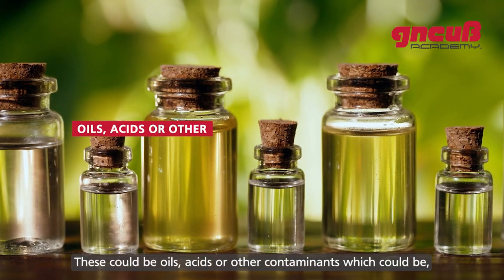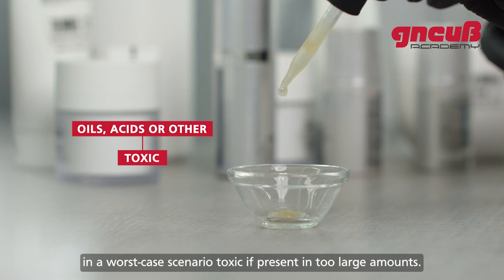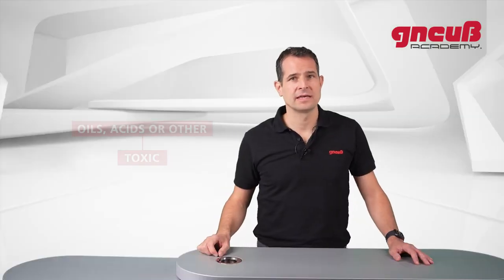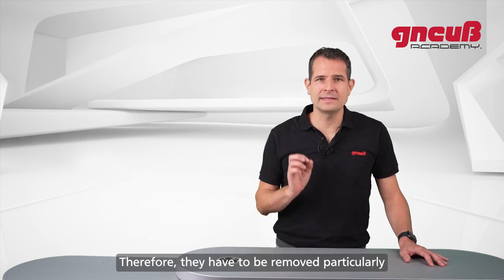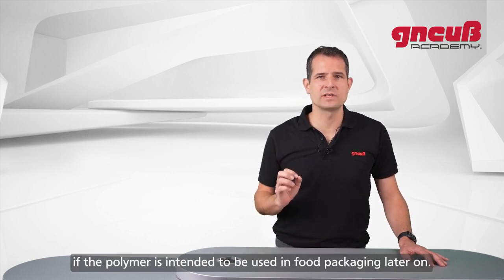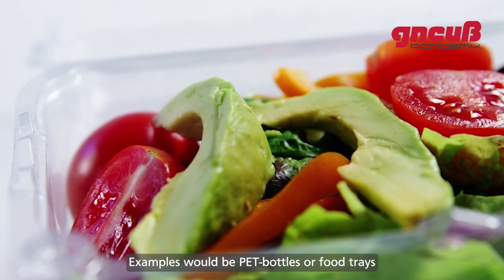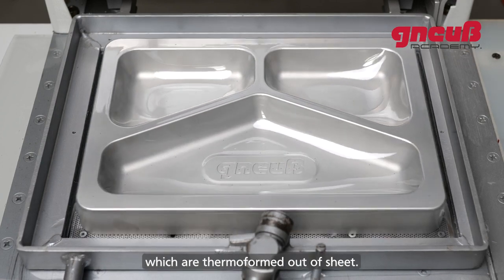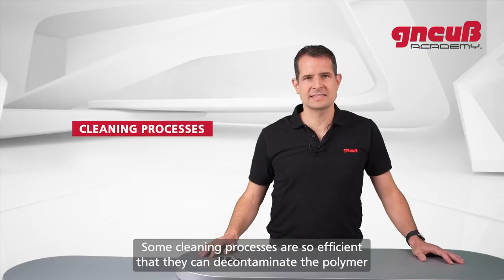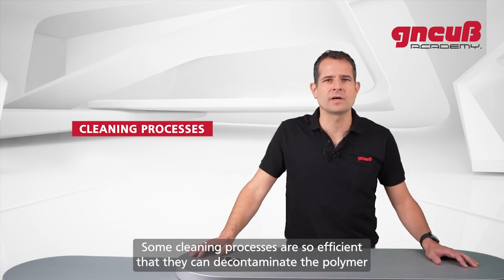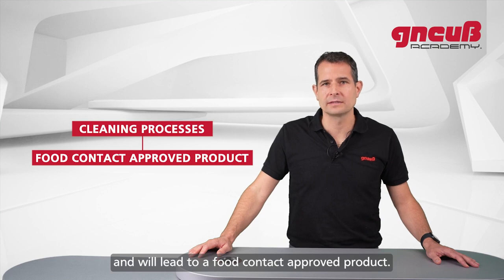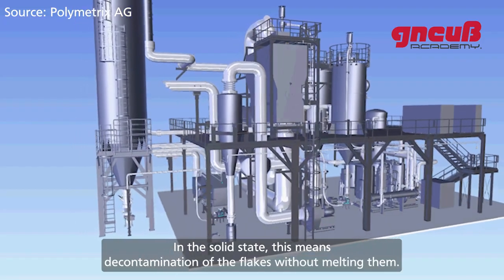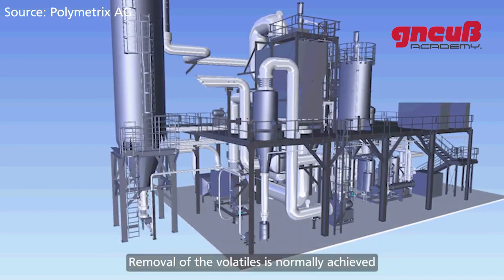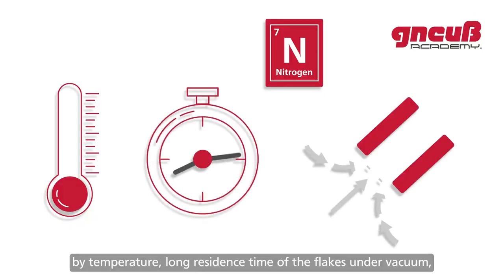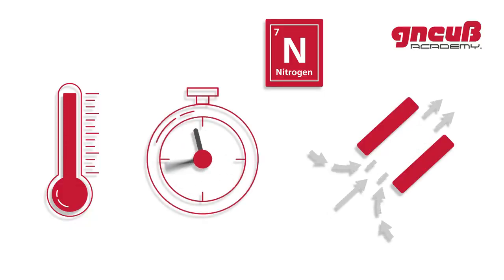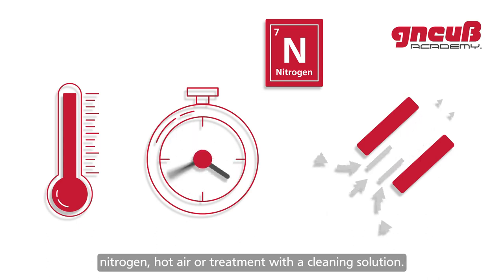These could be oils, acids or other contaminants which could be, in a worst case scenario, toxic if present in too large amounts. Therefore, they have to be removed, particularly if the polymer is intended to be used in food packaging later on. Examples would be PET bottles or food trays which are thermoformed out of sheet. Some cleaning processes are so efficient that they can decontaminate the polymer and will lead to a food contact approved product. In the solid state, this means decontamination of the flakes without melting them. Removal of the volatiles is normally achieved by temperature, long residence time of the flakes under vacuum, nitrogen, hot air or treatment with a cleaning solution.